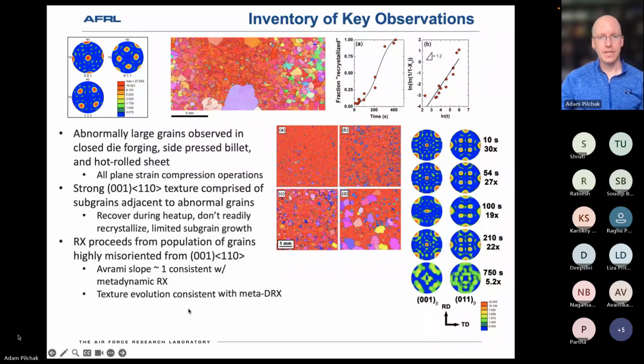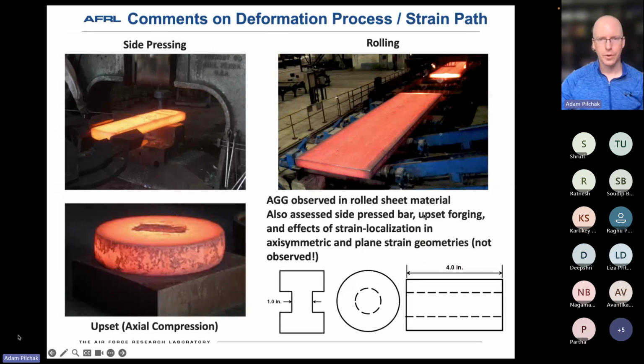We see that early in the annealing phase, we developed this really strong texture component that has some degree of subgrains in there. It doesn't appear that there's significant recrystallization happening during that annealing process. But once you dissolve all the alpha phase away, recrystallization then proceeds from those grains which are highly misoriented with respect to the average and dominant texture component. So, as I mentioned, we saw it in side pressed bars, rolling, and the closed die forging.